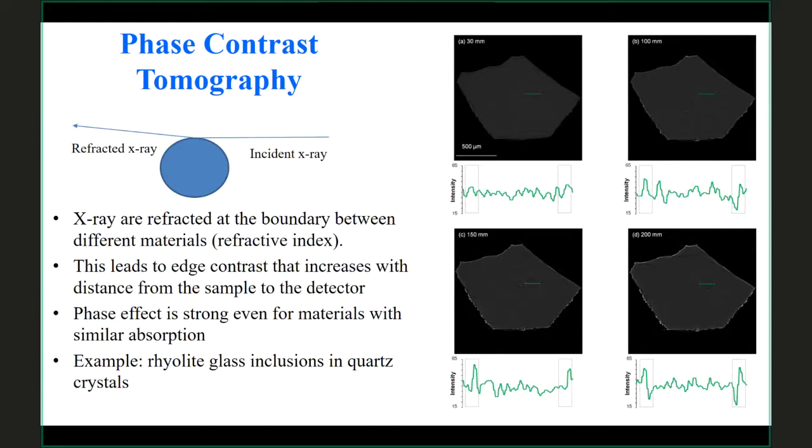So here's an example of rhyolite glass inclusions in a quartz grain. And this is a measurement with the scintillator to sample distance at 30 millimeters, 100 millimeters, 150 millimeters, 200 millimeters. And I think if you look at this 200 millimeter image, you can see that there's something that looks darker inside where this green line is, surrounded by a bright rim. And